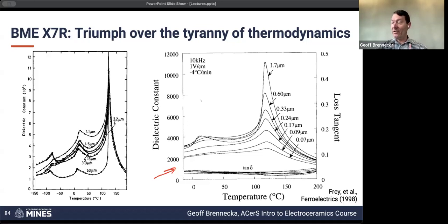Matt showed that as you get below 1 micron, those gains just plummet. So especially right at the phase transition temperature, you lose a lot of the maximum in relative permittivity that you see around a micron as you get smaller and smaller. So these are still very large relative permittivities compared to titania, which is about 100, or compared to alumina, which is like 10.